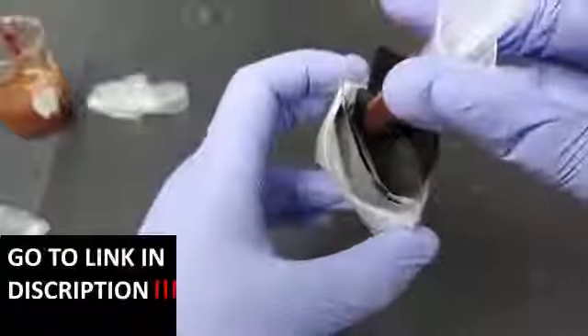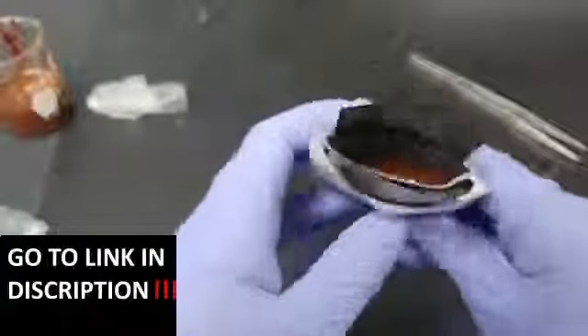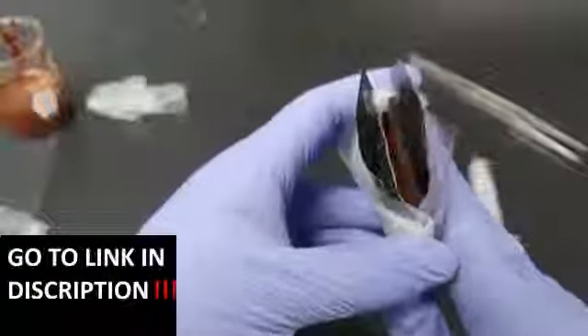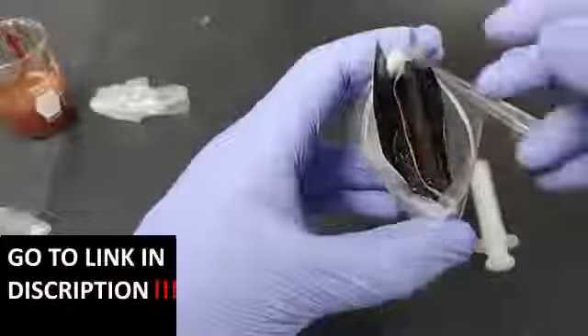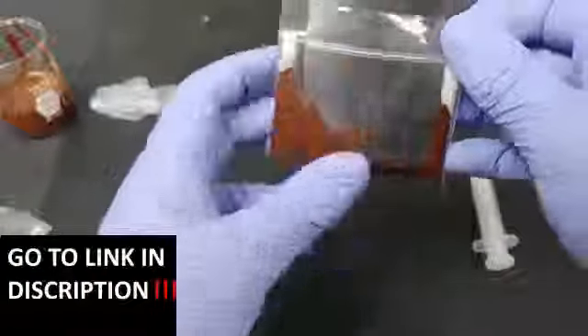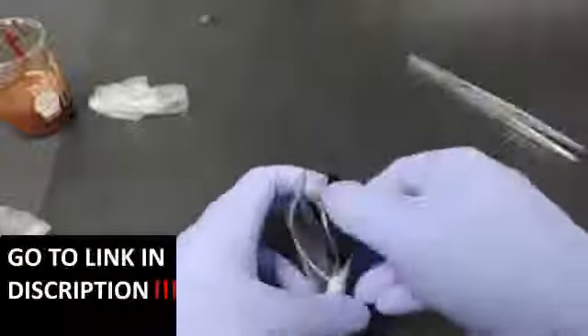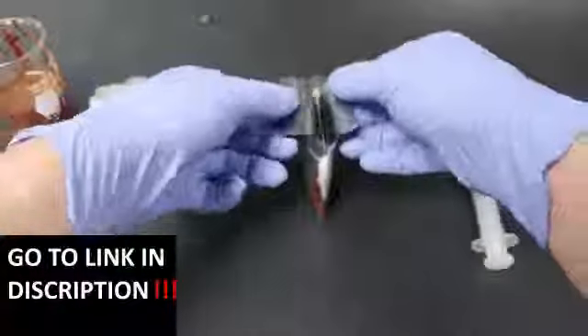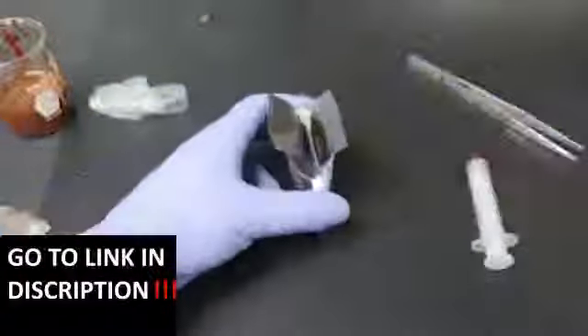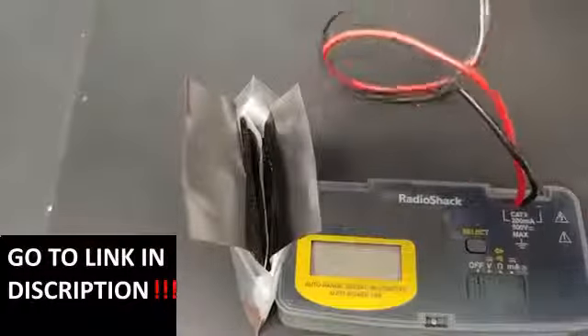One of the little tricks is you want to make sure that you wet that interface between the membrane and the carbon felt. That interface needs to be nice and moist to make a good connection. Second little trick is you want to make sure that those two graphite foil current collectors don't touch one another, or else it shorts the battery. So you want to be real careful about that.